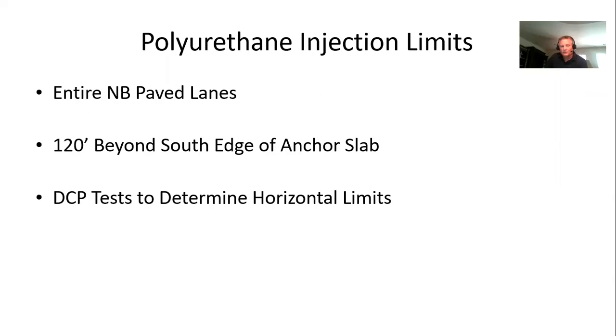which basically is almost what we used to use on drill rigs. We'd call a bullnose sampler, where we would just drive a steel rod down into the ground and read continuous blow counts. So for those who aren't familiar, DCP, dynamic cone penetrometer, I'll get to a little bit more detail on that as to the model that we use and some of the specs on that. But basically, it's a penetration test to supplement the penetration test from the auger borings that you had.